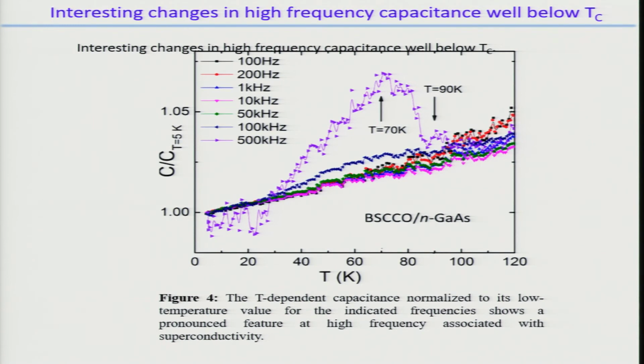And what's interesting about the BSCCO material is that we can measure capacitance. We see capacitance changes at the high temperature, where the pseudo gap presumably forms, but we also see some capacitance changes at high frequency. This is the transition of the BSCCO at 90 Kelvin, and we don't understand this yet at all. That there's something going on in the superconductor.